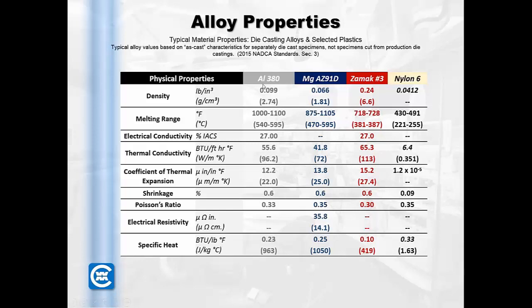Next one is aluminum, which is about 50% heavier than magnesium, and then we go all the way up to the Zamac or zinc families of alloys, which are in the 2.5 times heavier than aluminum range. So they're pretty bulky parts. So understanding the densities of each alloy, relatively speaking, is important. And again, we'll send out this information so that you'll have the entire breakdown of material properties.